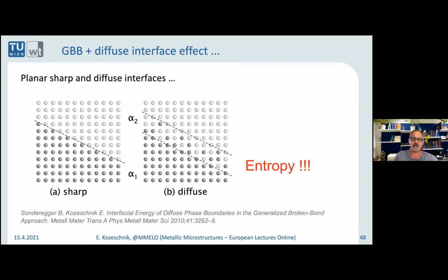There's another effect that we had to take into account, and that's the diffuse interface effect. That's an effect that takes into account that the interface is hardly ever really sharp. So there's always some atoms which are on the wrong side of the interface, and that will produce entropy. And this entropy contribution can be substantial if the precipitates, if the nuclei are, let's say, weakly bonded.